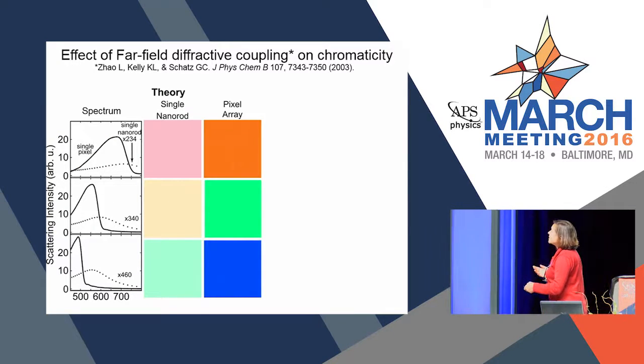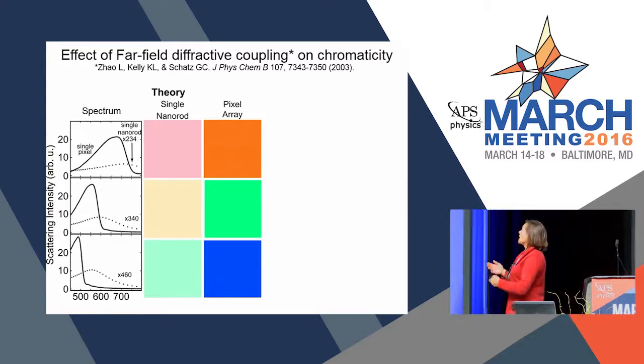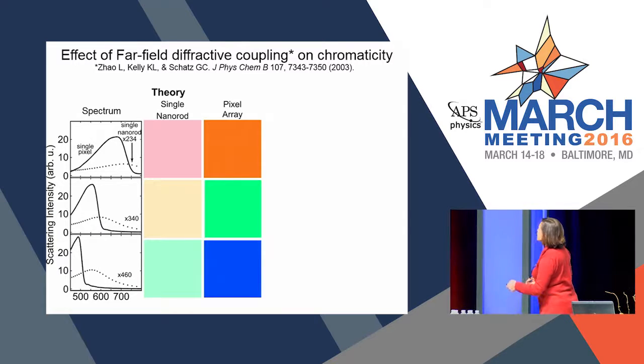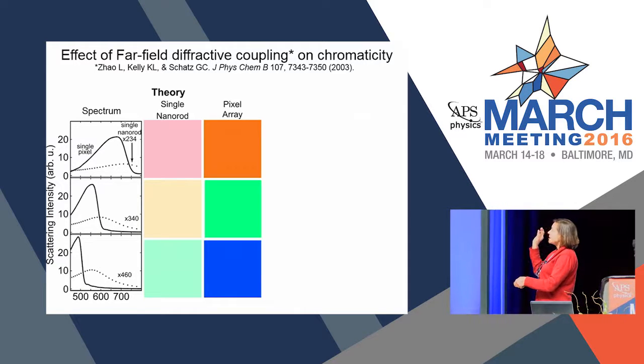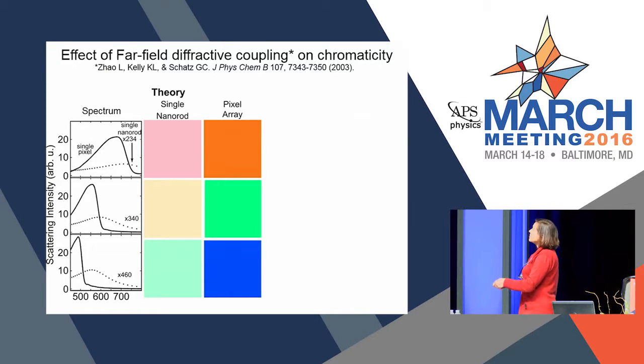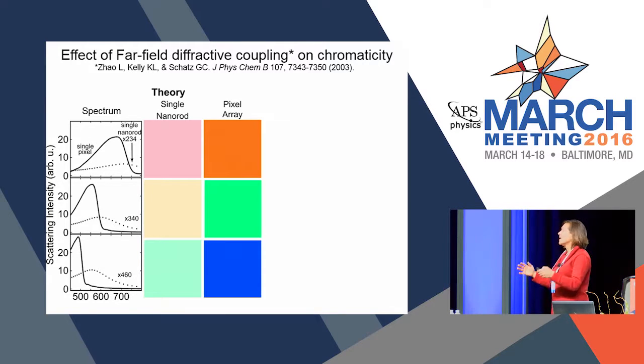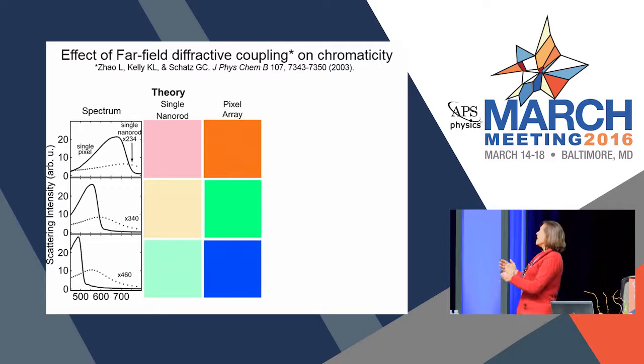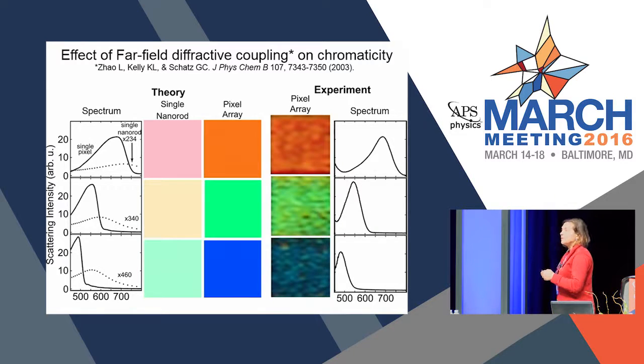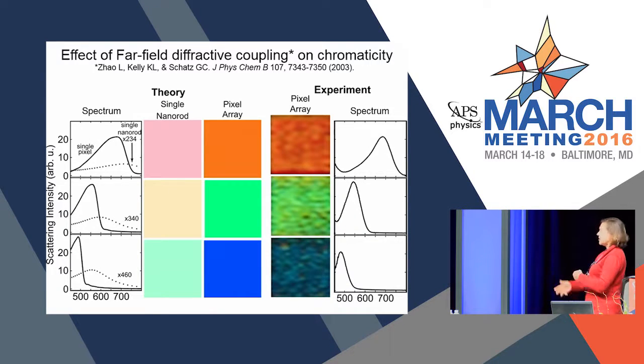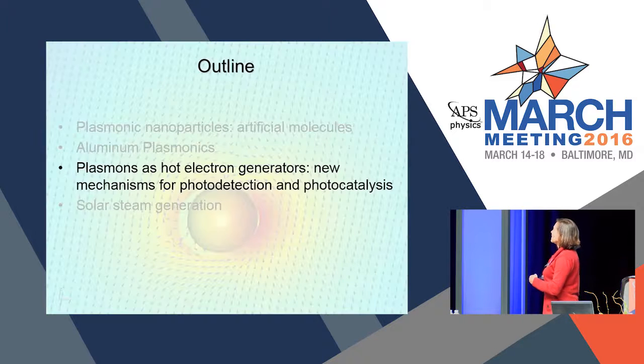And so the optical name for this is called far-field diffractive coupling, which gives rise to a very strong narrowing of the optical spectrum. And you can see here, if you just look at the color, right? The spectrum, of course, gives us a color. If we look at the color of an individual nanorod, we see these very faint, pale colors, which correspond to a very broad spectrum. If we used far-field diffraction and we use the array in intelligent ways, we can narrow the spectrum very dramatically and give rise to much more intense colors that actually will give us something that's red, green, blue accessible, that's completely competitive with what one can actually go to an electronics store and buy. So it's quite easy to do.